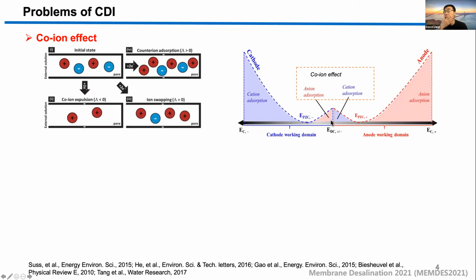Let's come to the mechanism for the co-ion effect. It depends on the potential of zero charge (EPZC) of the electrode. For example, if the EPZC of the anode is higher than the discharge potential, normally 0 volt, then during charging it will not only adsorb anions, but also desorb cations into the water. And the same on the cathode: if the EPZC of the cathode is lower than the discharging potential, then during charging it will absorb cations and at the same time discharge anions into the water as well.